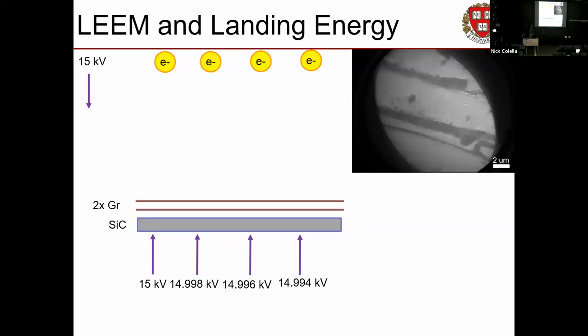And so a LEEM image is not really what we collect. What we collect is a stack of LEEM images taken at different landing energies, and then we go interpret them. And that is not simple at all. But okay, we're not going to worry about that. The idea is by changing how much energy the electron effectively lands with, we change how deep into your sample we probe. We also change the actual physics of interaction that's going on in the sample. Sounds weird. What can we see?